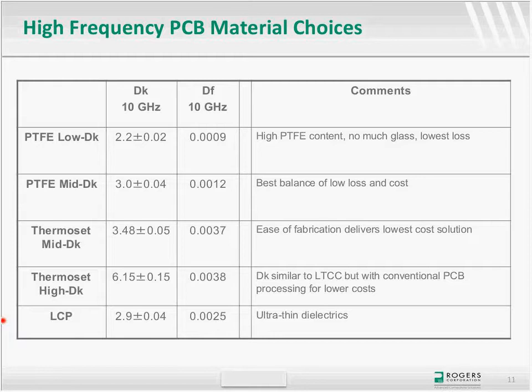We know of people who use some of the PTFE materials in lamination, so the raw PTFE ceramic of dielectric constant 10, to use that as a bond ply, but that requires taking the multilayer to a very high temperature lamination. In essence, you are remelting the Teflon and using that as your bond ply in what's called fusion bonding. So not many facilities have the ability to go to the required temperatures of 325 Celsius, but some people can, and some people have done that. So it is something that is possible.